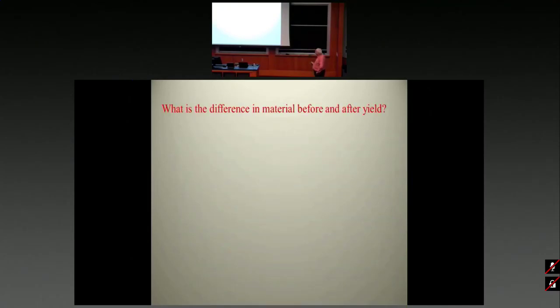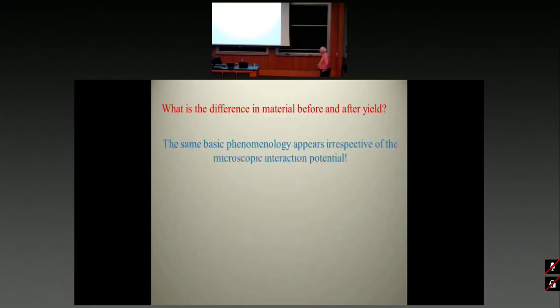So, as I say, what we were interested in is what's the difference in the material before and after the yield. Now, the observation is that the same basic phenomenology appears irrespective of the microscopic interaction potential. Whether I do it on the computer with Lennard-Jones interactions or with soft spheres or with hard spheres or whatever, if I do it in experiments with metallic glass or polymeric glass or structural glass, always you have the same phenomenon that I showed here, that you have an elastic or quasi-elastic regime, and then a yield, and from that point on, the system cannot increase its stress when you increase the strain.